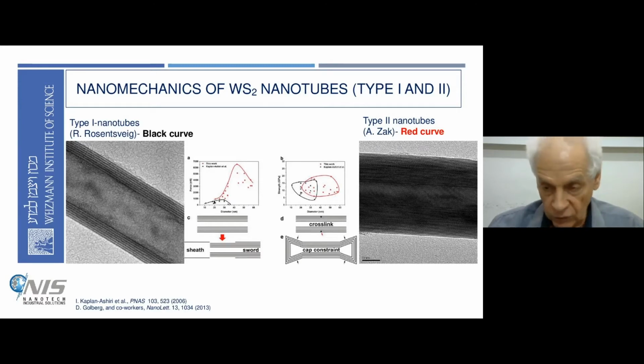However, the thick nanotubes, as you see here, have a lot of defects, and these defects pin the layers together, so that if you pull them apart, all the load is taken up by all the layers, and consequently you get much higher forces. This is the red curve here, much higher force. You can pull them apart and they would not break until 20 gigapascal. Just to give you an imagination, 20 gigapascal is equivalent to 20 tons applied on your nail. So it's a very, very big force, and yet they do not fail, which shows that these materials are extremely good for a variety of applications, which you will see in a minute.